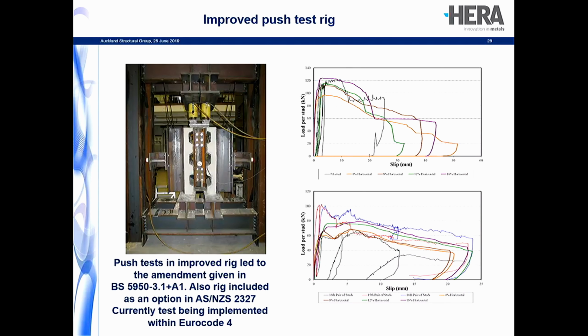And champagne corks started popping. We found out that the performance in a beam was significantly better than that suggested in a push test. It's badly shown here, but whereas in the previous slides where I showed maybe you would get 3 or 4 millimetres worth of slip, we're getting 15, 20 millimetres worth in the beam test.